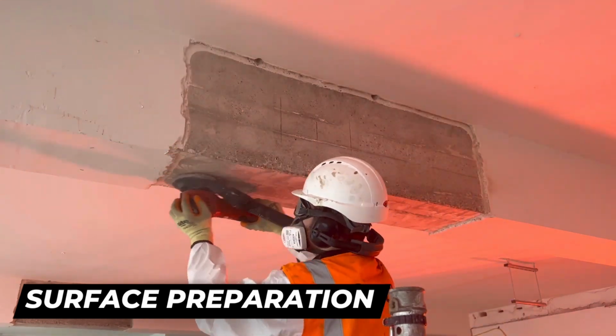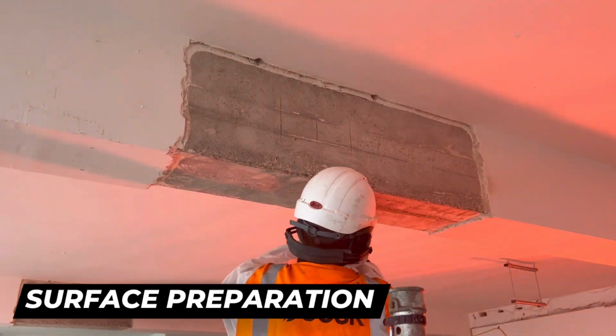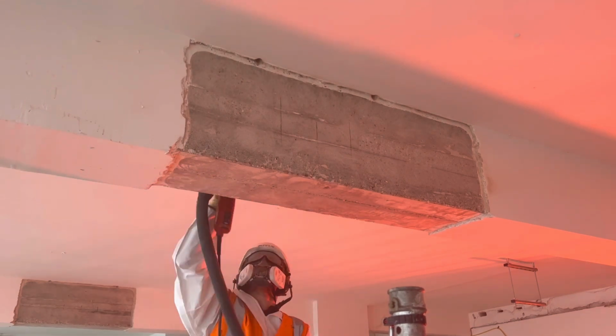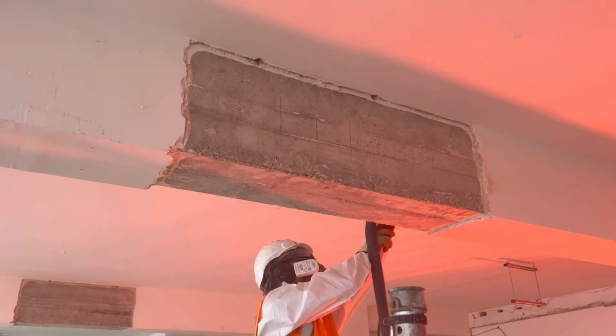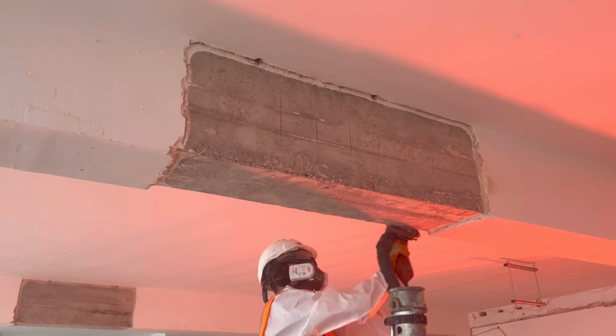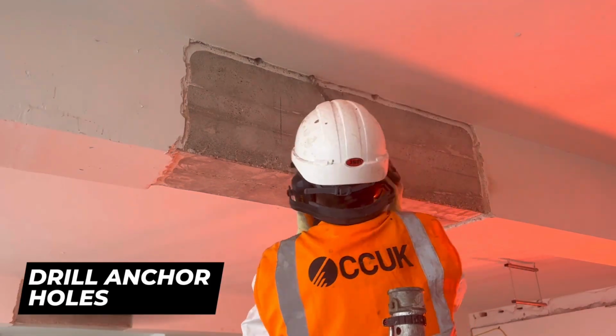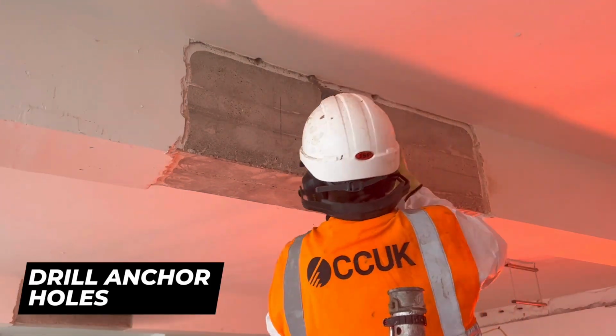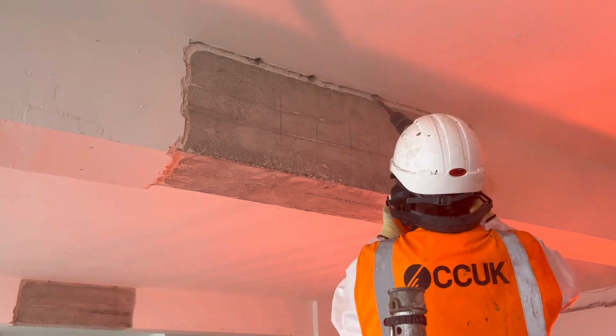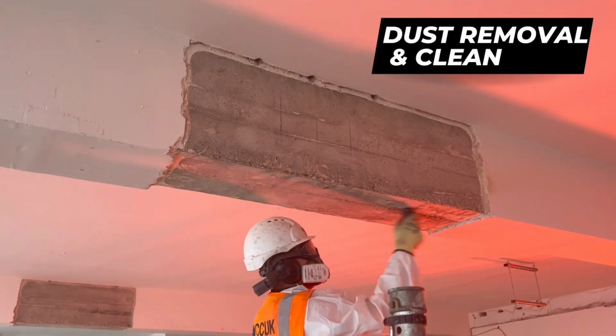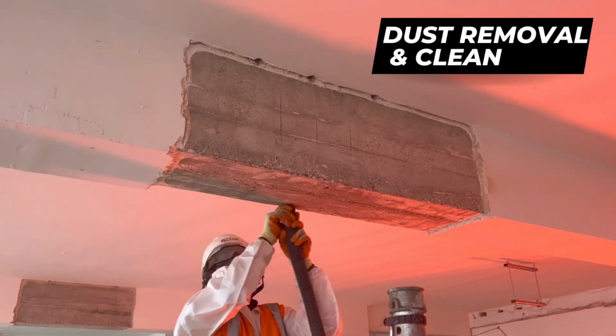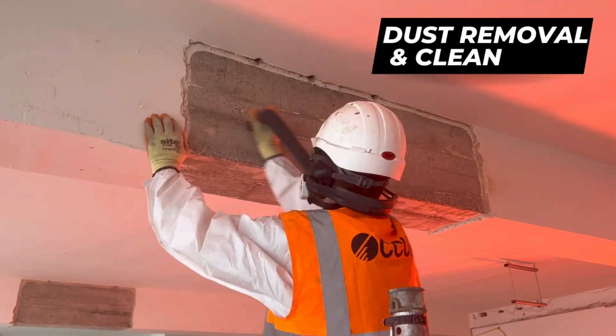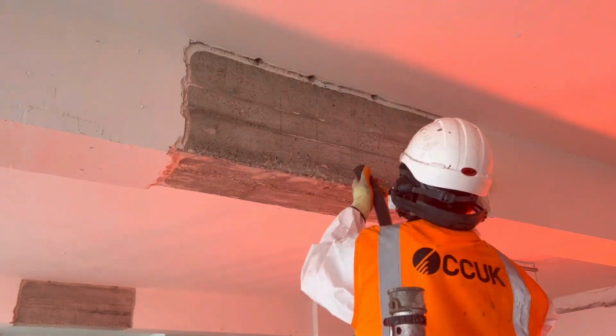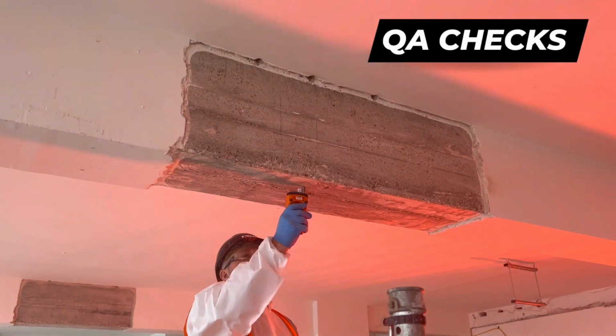So the first thing we do is surface preparation, which you've seen them doing by diamond grinding. Then they have to clean the area by vacuum so that it becomes dust free. They have to drill holes for the anchors, and clean them as well. Then there is a QA, QC check. They have to measure the temperature, humidity and all those things to make sure that this is the correct environment to apply FRP. Then they do priming, which is done using pure epoxy.